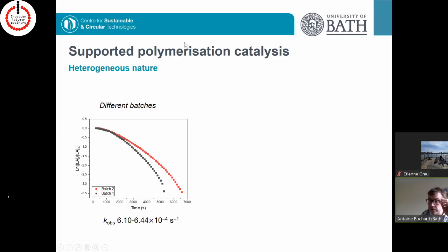So, because there was an amount of leaching that we could see, we tried to investigate: is the catalysis actually heterogeneous? Is it really the beads and the metal supported on the beads which is doing the job? So we looked at different things to try to confirm this heterogeneous nature. We had a look at different batches, because that could also be an indication. If there's too much variation, that could be an indication that the amount which is trapped or leached depends on how you wash it. But when you look at different batches, the activity and the rate constant were actually quite similar.